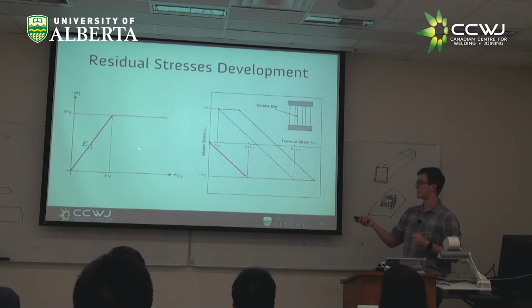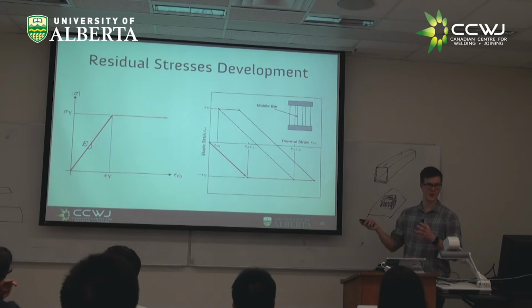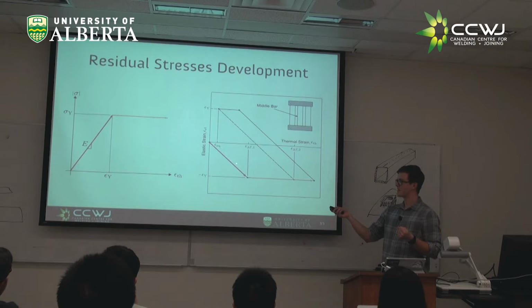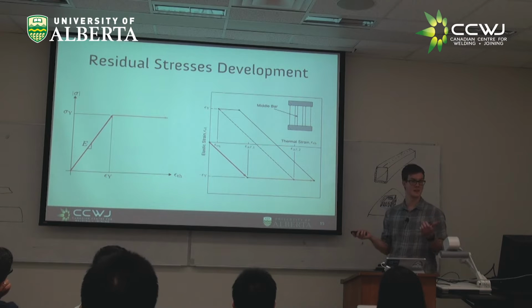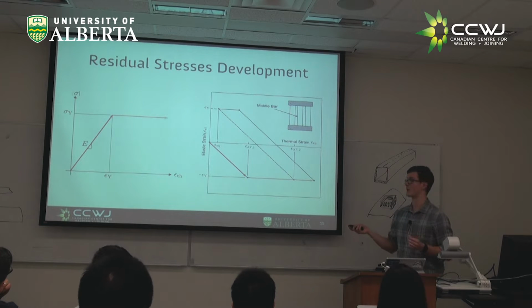But in welding, we could have any amount of thermal strain. We're going to go up to some very high peak temperature, we have a lot of thermal strain, or we go up to a lower peak temperature. So already, hopefully you can imagine, if this is our thermal strain, that's our peak temperature in welding. So you can imagine material that's really far away from the weld has a fairly low peak temperature, right? Which means you might not even get hot enough to yield. If you're really far from the weld, you might just go here and go back. You cool. You have no residual stress. At least you would predict no residual stress with this simple model.